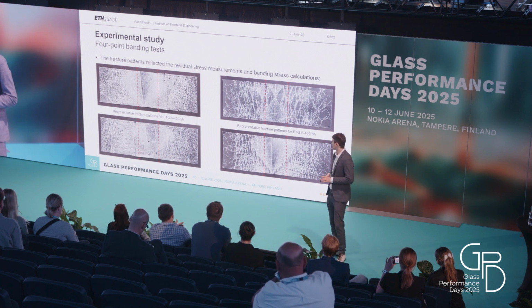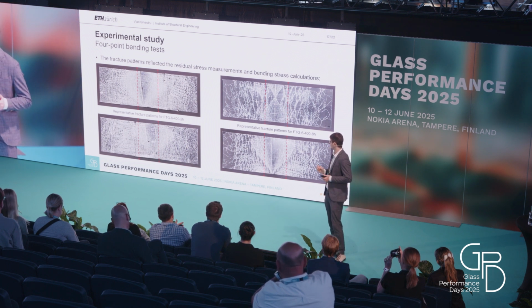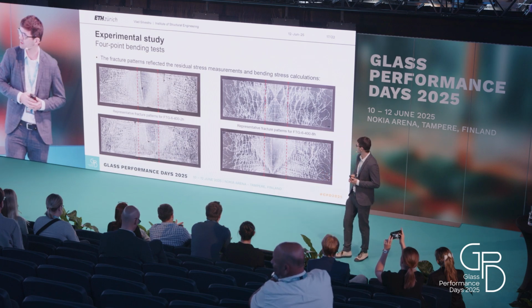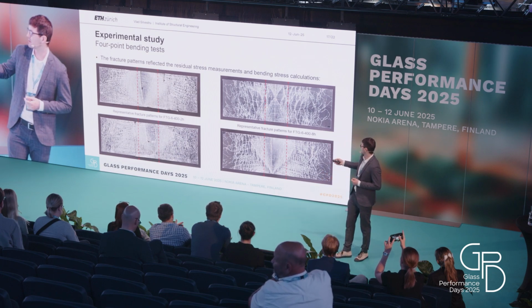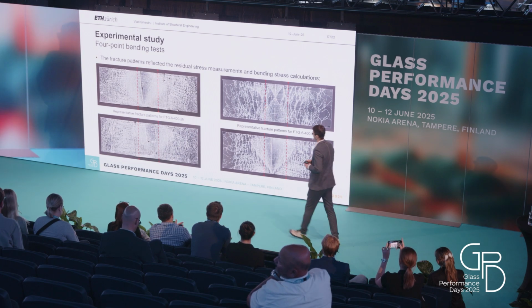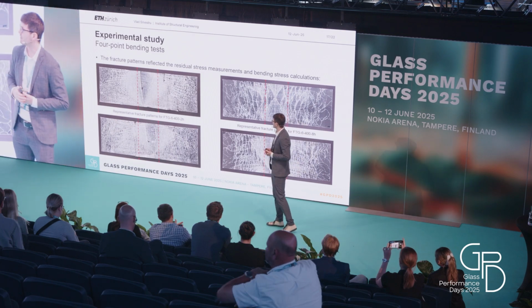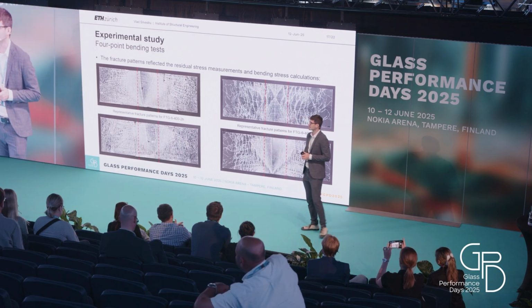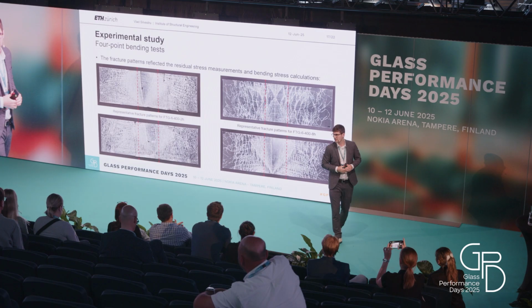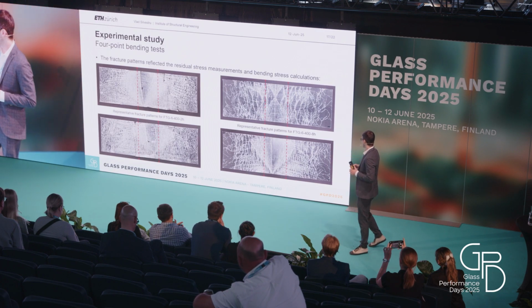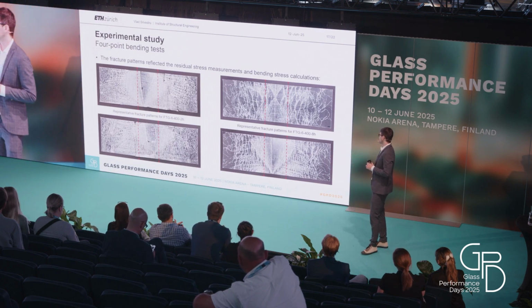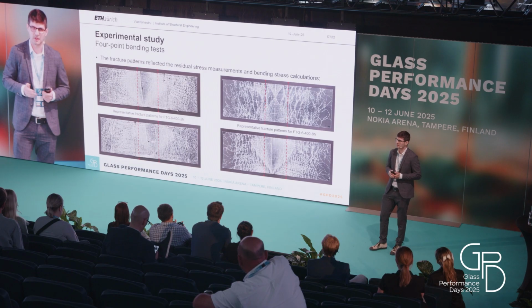the crack pattern shows still quite small fragments. We can see a little bit the radial distribution of the cracks, but I would say it's still quite typical for fully tempered glass. After 8 hours of treatment, it already looks more like a heat-strengthened glass, maybe.